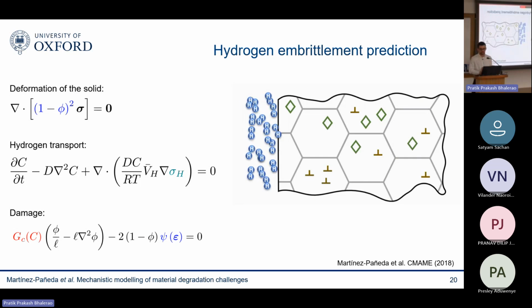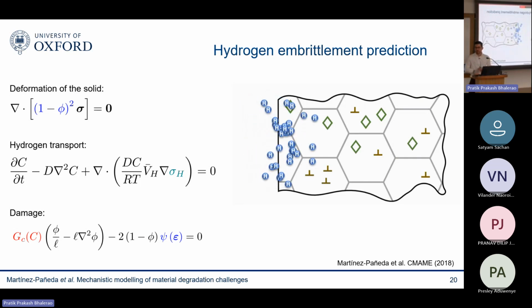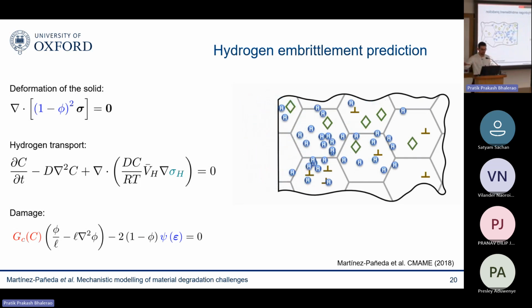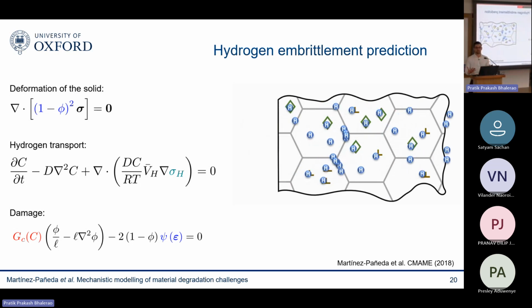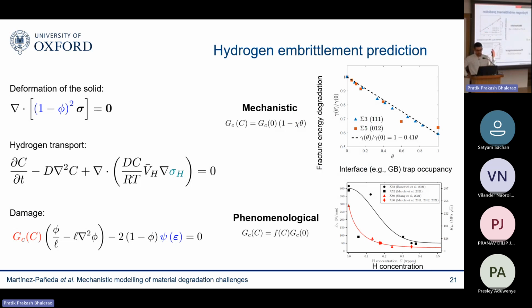But I want to spend a bit more time on the damage process itself. So now you know how much hydrogen you have, where and when. And the idea is to see how this affects your resistance to nucleate and grow cracks. There are a couple of ways you can do that, and we have proposed two ways. The good thing is that the framework is quite universal. So whatever way you want to reduce your fracture energy, you're welcome to try it. Many groups have taken our framework and expanded it in multiple directions, because there are different interpretations on how hydrogen actually degrades your fracture resistance. And this can also change between the material and environment.